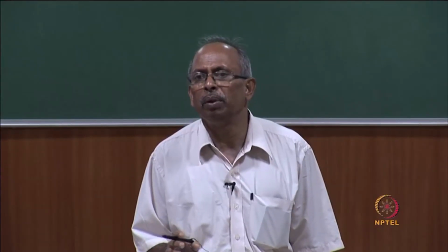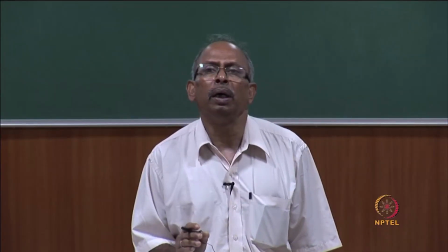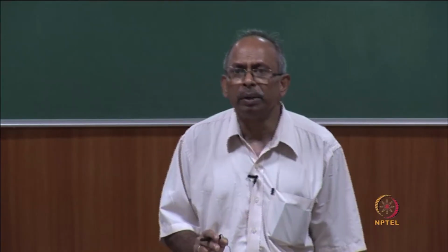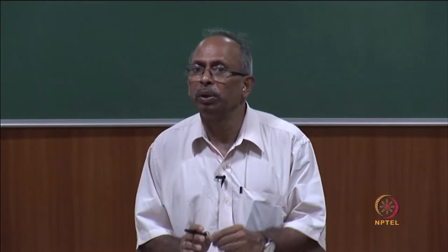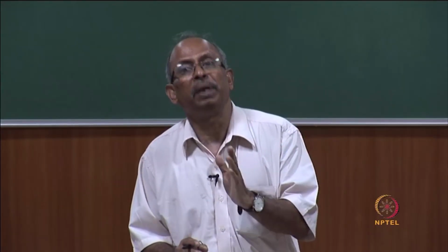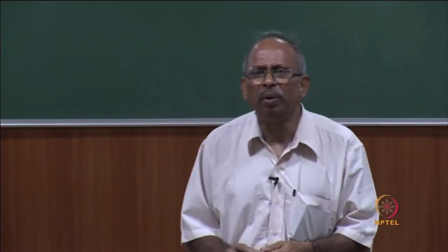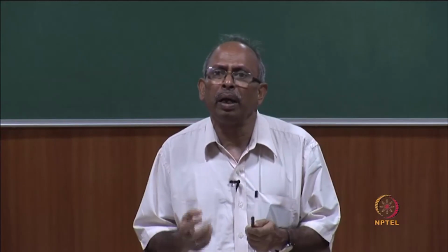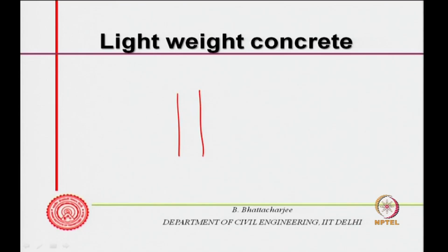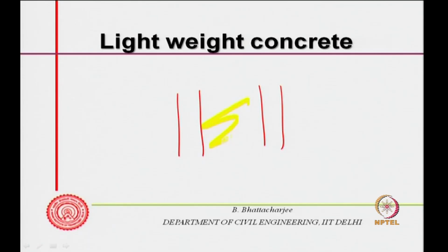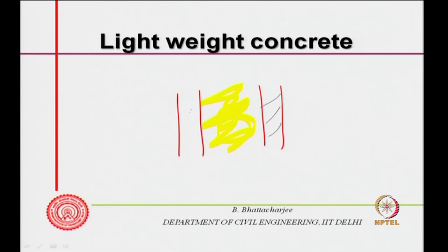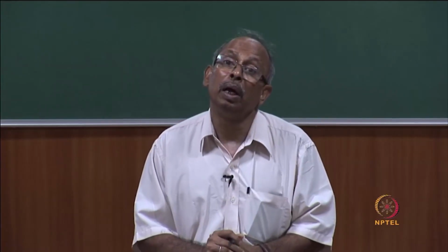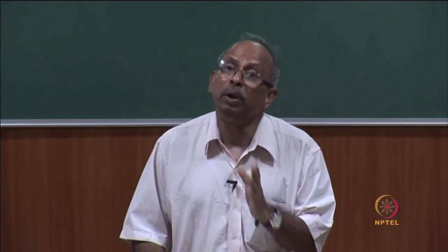Of course, by the porosity at the surface, they can provide you some kind of sound insulation. Sound insulation actually is a function of the mass of the wall, larger mass more insulation, but the absorption property is a function of the surface. So, if you have a porous surface, that absorbs more. Lightweight aggregate concrete can also be used as a core in a sandwich panel: you have one panel, another panel, and a third sandwich material here. This outer material will take the load, and the inside material can be lightweight material, which will act as thermal insulation. The whole system can give you good acoustic insulation also, because a layered system gives good acoustic insulation as well.